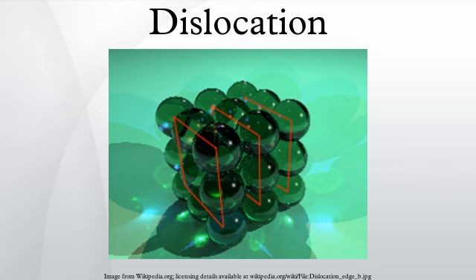Field ion microscopy and atom probe techniques offer methods of producing much higher magnifications and permit the observation of dislocations at an atomic level. Where surface relief can be resolved to the level of an atomic step, screw dislocations appear as distinctive spiral features, thus revealing an important mechanism of crystal growth. Where there is a surface step, atoms can more easily add to the crystal, and the surface step associated with a screw dislocation is never destroyed no matter how many atoms are added to it.